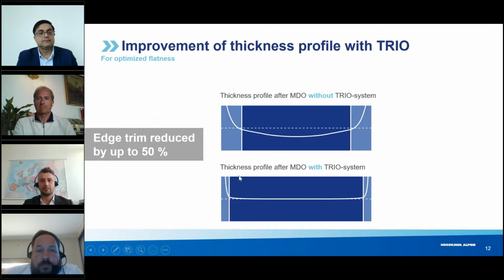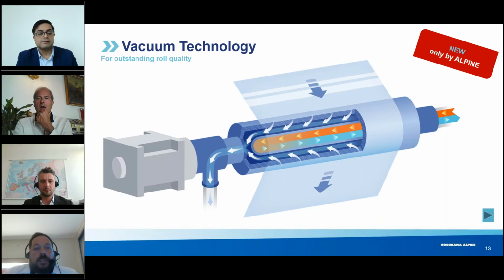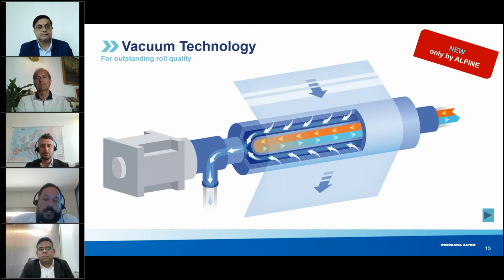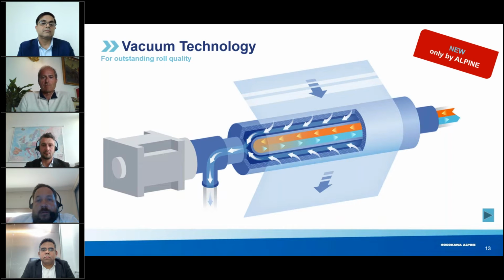If we use our trio system, then you have a flat and even film profile with less trim wastage. The second thing is our vacuum technology. That means that the second stretching roller is a microporous roller where a strong vacuum is applied. This leads to the film being sucked very tight on the roller, and the necking is prevented. This will also help to create a better film flatness and also to prevent web breaks during the stretching process.